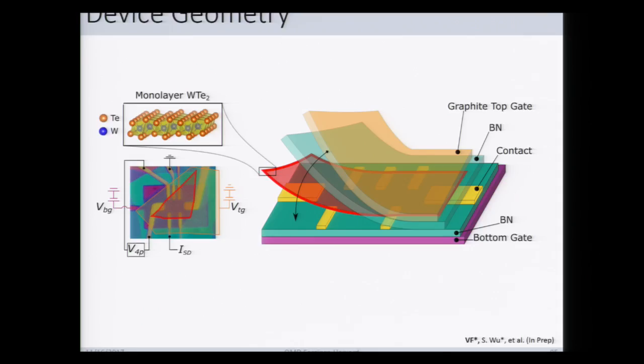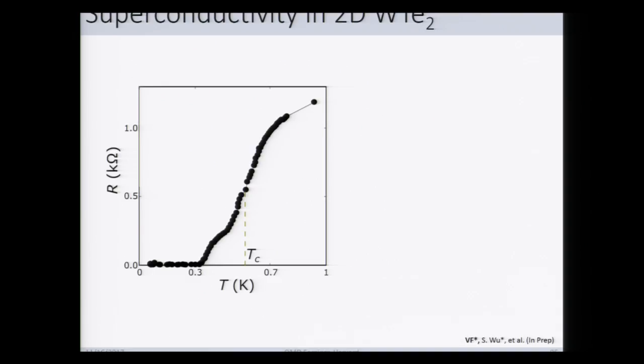So we then followed up with a new device geometry that allows for a full 4-terminal structure, which allows in particular that between every set of contacts, you will have tungsten ditelluride that is sandwiched on both sides and protected from oxidation. And this would hopefully allow us to measure zero resistance and prove that the system is indeed superconducting. And it does work.